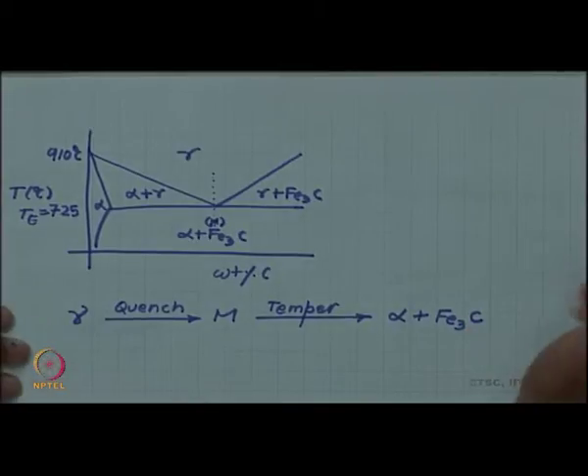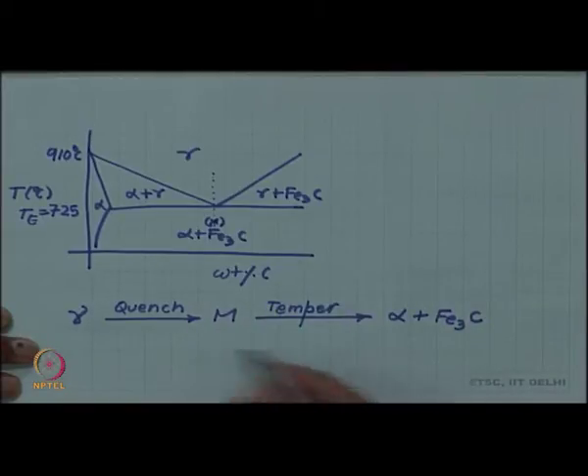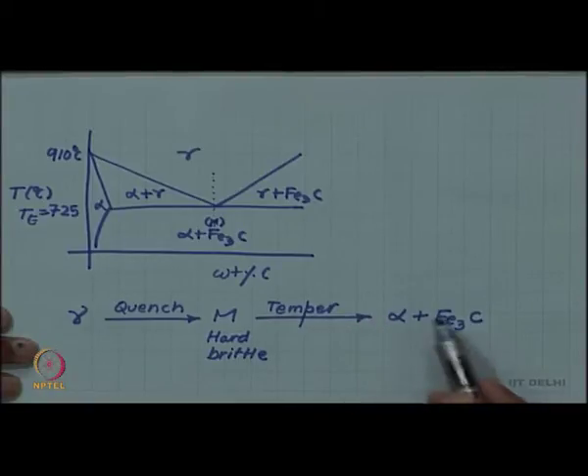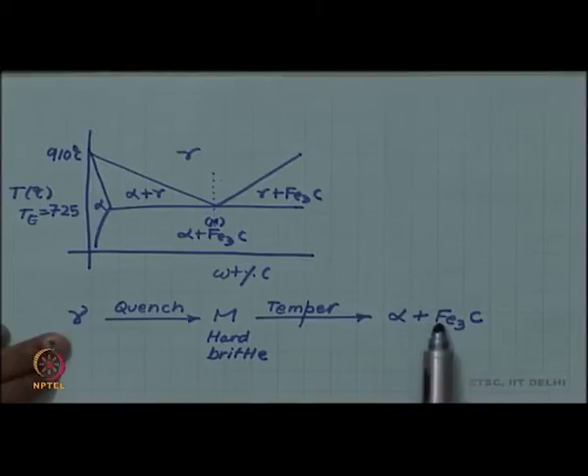Question may come to your minds that why are we going through this circuitous route, that first we quenched to form a metastable phase martensite which was hard but was also brittle and then we again heat it. There is an additional cost, additional time involved to get alpha plus Fe3C. If alpha plus Fe3C was what was desired, we could have directly got by cooling of gamma, slow cooling of gamma directly would have given me alpha plus Fe3C without going through this intermediate martensite, without going through that excessive effort and cost of quenching. As we have seen that slow cool will give me coarse pearlite by annealing or fine pearlite by normalizing. I could have got alpha plus Fe3C simply by direct cooling of gamma, there is no need to quench and temper.